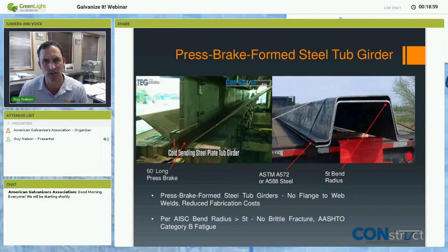Getting specifically into the press brake form steel tub girder, you can see here the press brake on the left. That is the die, and that is usually the limiting factor. Usually the press brake is 60 foot long. The die itself comes in lengths up to close to 60 feet long. So we found that 59.5 was about as long as the die we could find.